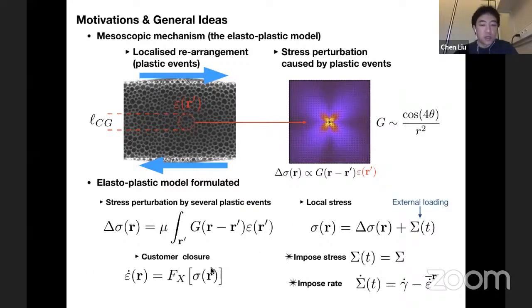But then there's a third part, which is very important, the constitutive closure, which relates the local plastic strain rate to the local stress. And this is the most variant part if you look across the literature in elastoplastic model approaches to the rheology of amorphous materials. Okay, so this is the main part that I'm going to talk about.